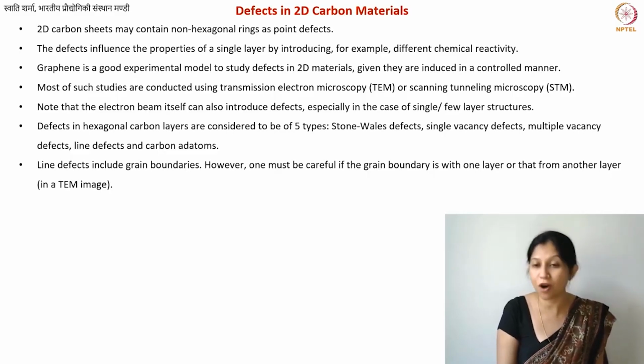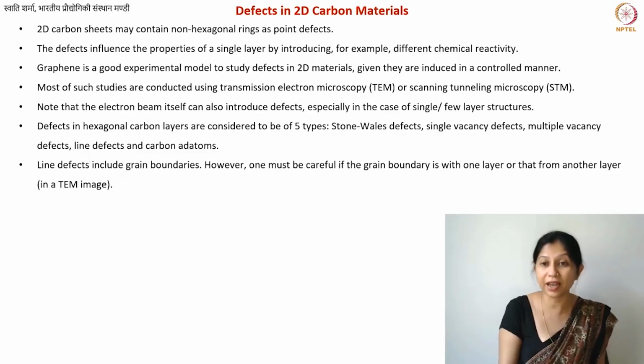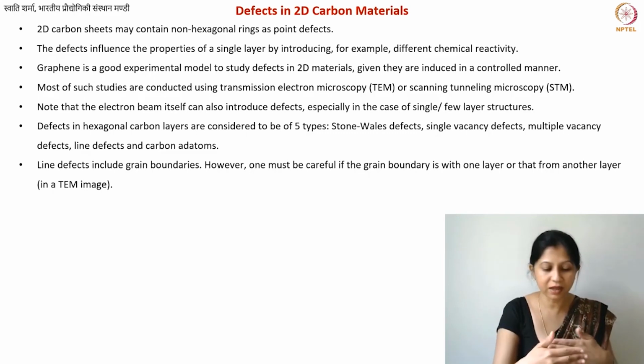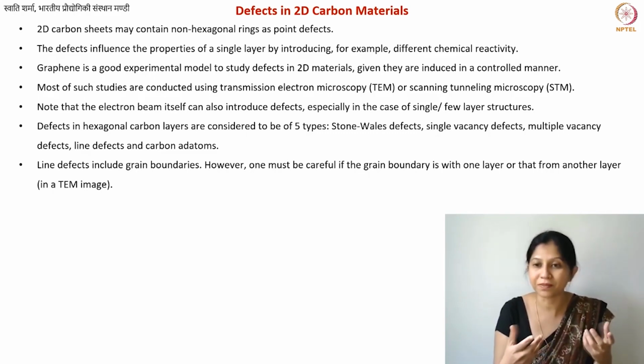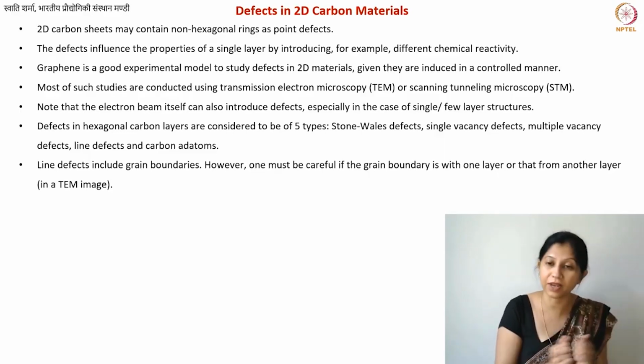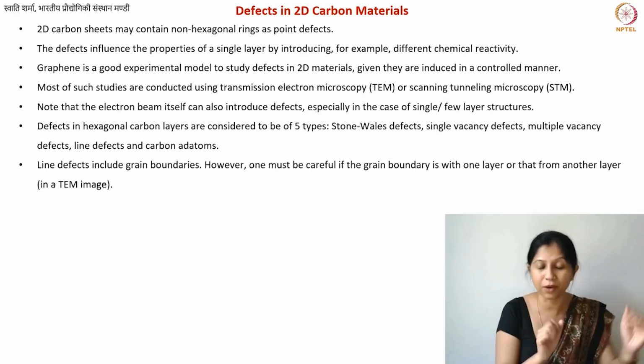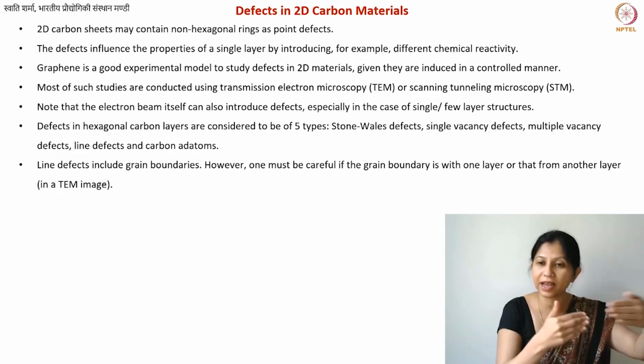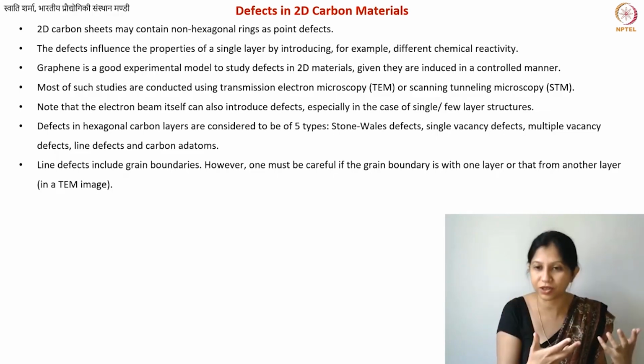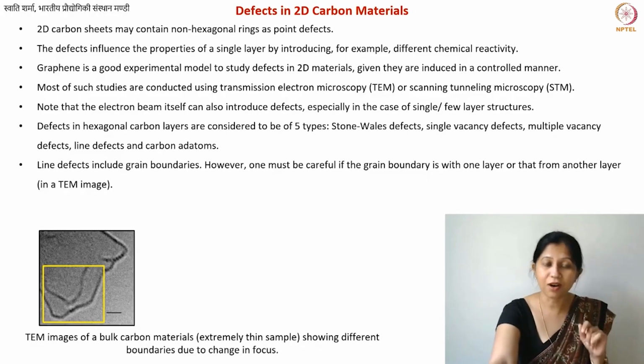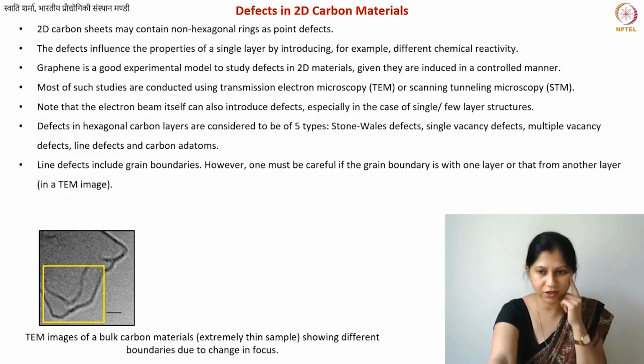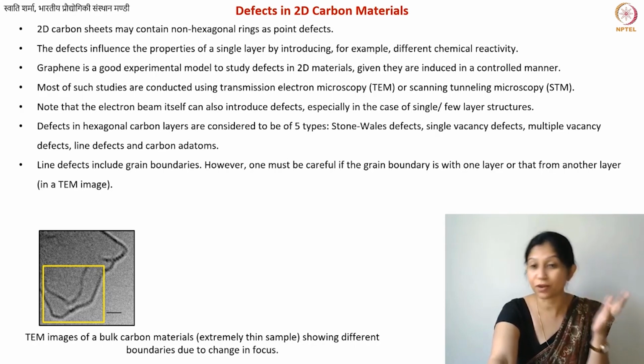So what you often end up doing is this TEM and STM imaging, and I already told you that one problem with that imaging is that you may end up introducing defects. Another problem is that TEM images are 2D projections of a 3D material. Let's say you have 10 layers of graphene, 10 sheets within your focal plane. In that case, you will not be able to get any depth perception. So here is the image again. This was taken when we carbonized phenol formaldehyde resin.